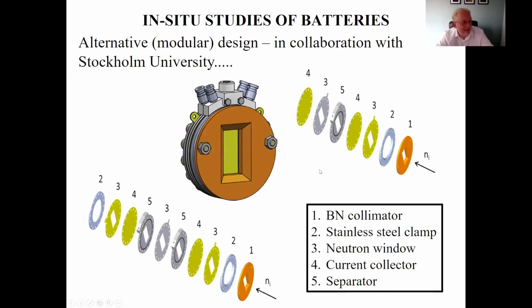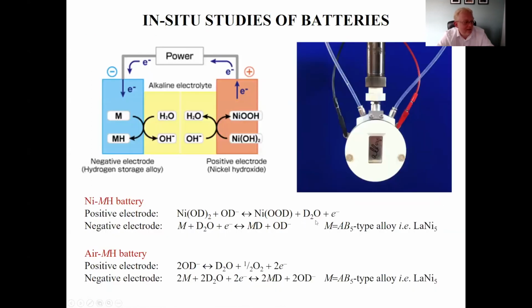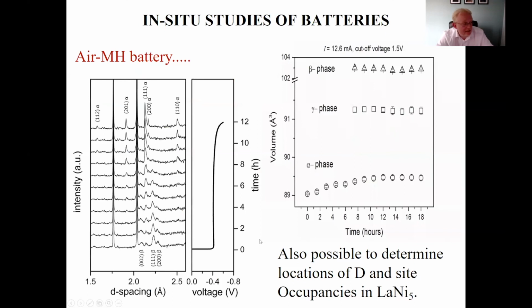And then finally, we have one other type of cell that we've built. And this one, we have current collectors, and you deposit your material on top of this vanadium screen, and then you arrange it so you're only looking at one of the electrode surfaces at one time. This is what it looks like, and you collect Bragg information on that material as you go through the charging and discharging process, and you can see the phase changes and the relative proportion of those phases on that charging and discharging cycle.